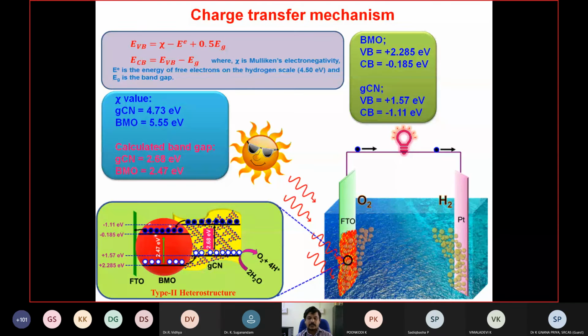Okay. Now I have done everything. I have prepared the material, I have studied the material, I have checked the stability, everything we have done. Now I have to propose the charge transfer mechanism. For proposing the charge transfer mechanism, we have calculated the valence band as well as conduction band positions by using the Mulliken equation. We substitute the standard values available in the literature. We have also calculated the band gap